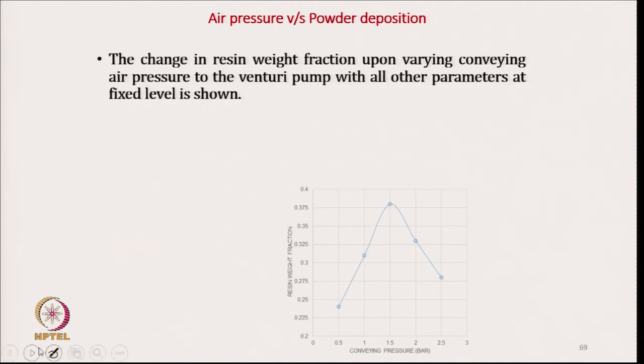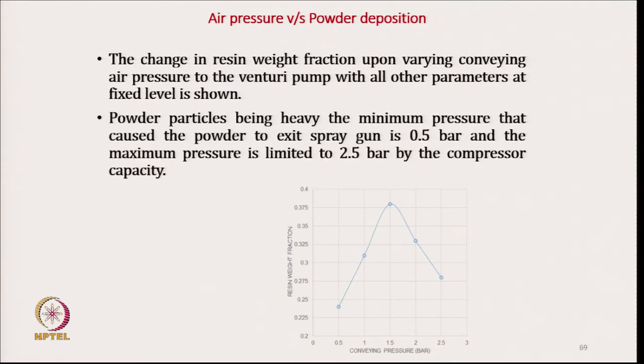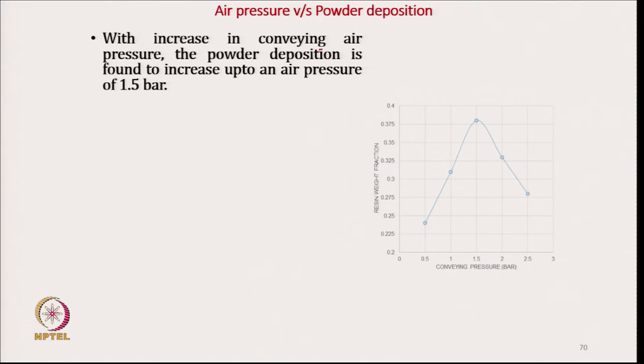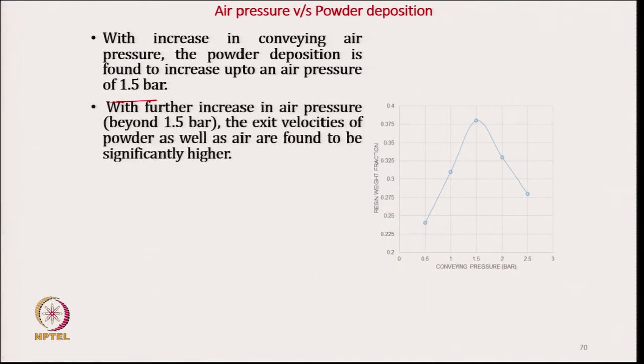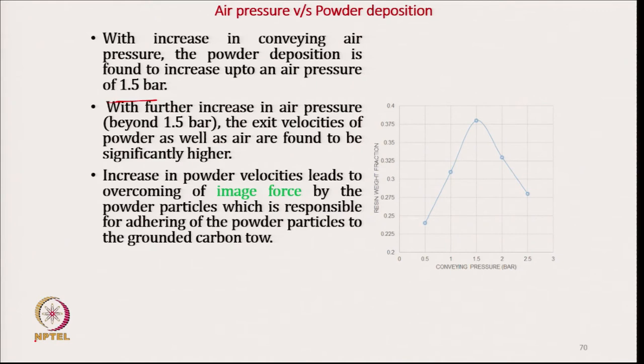So, this is attributed to the change in resin weight fraction upon varying air pressure. As we increase the pressure, the powder deposition is found to increase up to 1.5 bar and beyond that there is a significant decrease. The increase in powder velocity leads to overcoming the image force of the powder particle, which is responsible for adhering the powder particle to the grounded carbon.